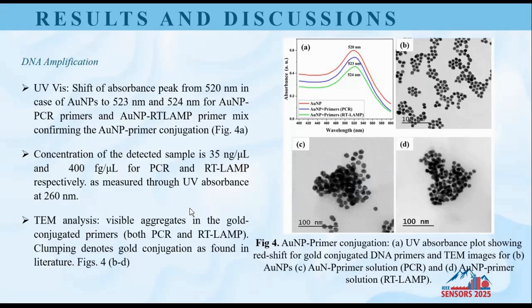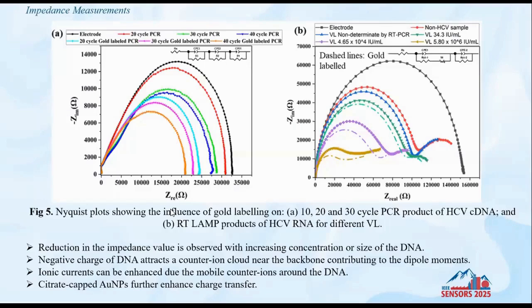So the concentration of the detected sample is 35 nanogram per microliter and 400 femtogram per microliter for PCR and RT-LAMP processes respectively, as has been measured through UV absorbance at 260 nanometers. Regarding impedance measurements, impedance values are characterized by reducing arcs with increasing number of PCR cycles and further with gold labeling. The progressive drop in impedance with the increasing concentration or size of DNA is primarily attributed to the electrochemical changes in the solution. As the DNA has a negative charge, a counter-ion cloud is generated near the DNA backbone, contributing to the dipole moments.